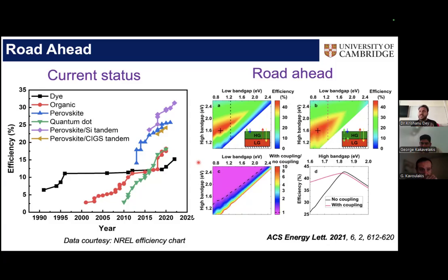But again, it doesn't really matter. In our paper, the supplementary information is pretty long, so you can have a look there. We have also done the A-site variation, which I'm not showing here. If you have an FAMA, the overall trend is still the same. It's just that there will be more ion migration in both cases. The problem is MA can rotate pretty easily, so it has a dipolar disorder as well, which has its own effect when you do temperature dependent measurements. But ion migration wise, the trend is still similar.